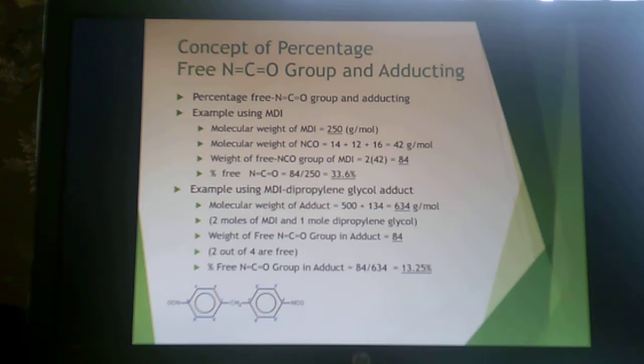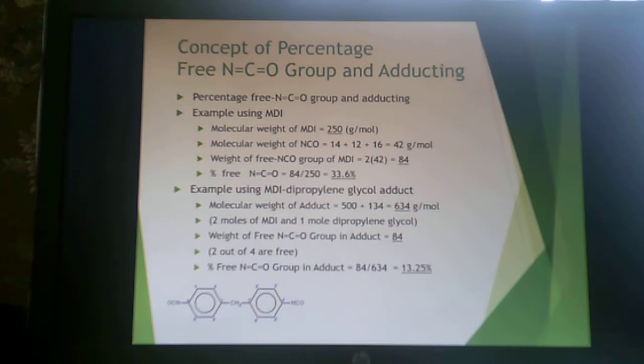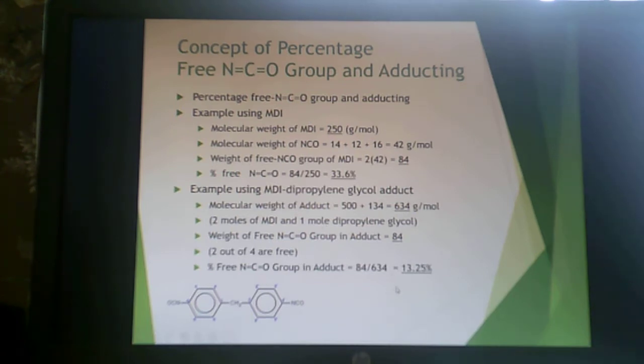You can create an MDI dipropylene glycol adduct, grow molecular weight, and it reduces the amount of free isocyanate in the adduct. Some of the isocyanate has been reacted to advance molecular weight, so you still have growth of molecular weight — it just hasn't participated in cross-linking. In the case of just small molecule MDI, you have about 33.6% free NCO. When you react two moles of MDI with one mole of dipropylene glycol, you reduce that by over half, and that also reduces the sensitivity to moisture.